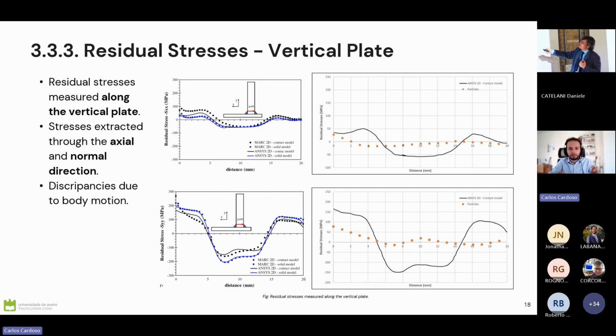Since the two grips, the two fixed geometries on top of the vertical plates, were released, the tack welds alone were not sufficient to keep the structure completely stable during welding, and those small displacements were enough to make the particles measure not the exact same locations.